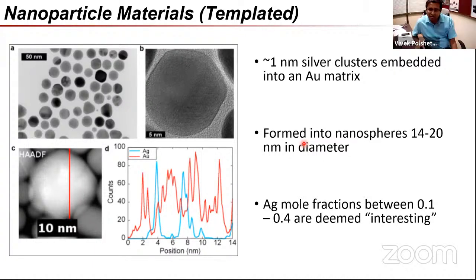But then practically it could be a mixture of both, right? There could be some amount of silver on the surface, certainly. We believe that is not the case because silver can be etched and oxidized chemically in certain ways, and this material doesn't. So it seems to suggest there's no free silver on the surface. But there's no physical evidence other than that, which I can offer to you, which would be completely compelling that all of my silver is inside.